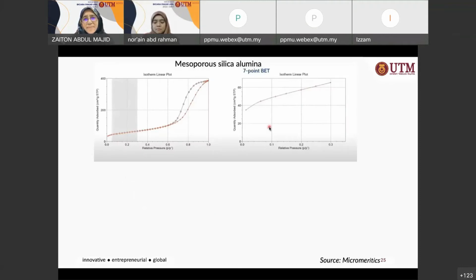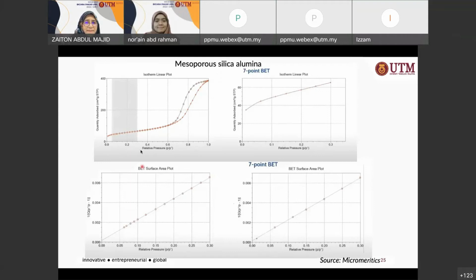Okay, so this is an example which I took from the Micromeritics website, an example of a mesoporous silica alumina. If you look at this mesoporous silica alumina, what they did is they did it two ways. They did the linear isotherm, and from there they ran a BET surface area. Another one, they did just a 7-point BET.